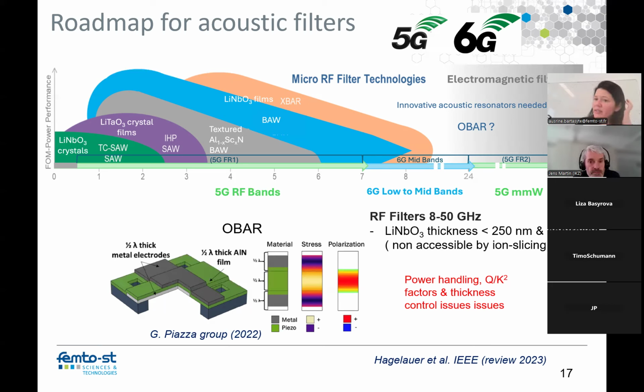And then other techniques came, for example lithium niobate ion slice films, which are very thin, 250, 300 nanometers thick. Then it can be integrated in the same bulk devices. I will show some examples after. And then there are also X bars, where a more lateral excitation came. So it could probably go to 8 gigahertz, something like this, because lithium niobate is about 3 times more coupled than aluminum nitride. So it helps to go to much higher frequencies.